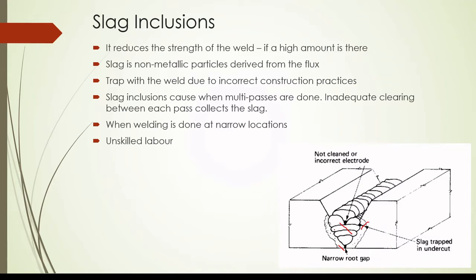Within two welding passes, there could be slag within the weld. When there are several passes of welding done, if one does not clean the slag or does not remove the flux completely, it will remain. We have to be very careful and take adequate actions to remove this slag completely. Other reasons include welding in a narrow place where it may be difficult to clean, and use of unskilled labor could also be a reason for this kind of issue.